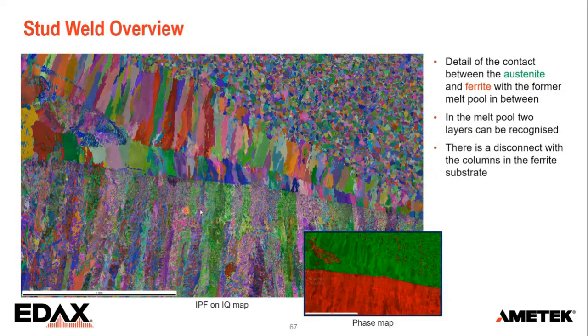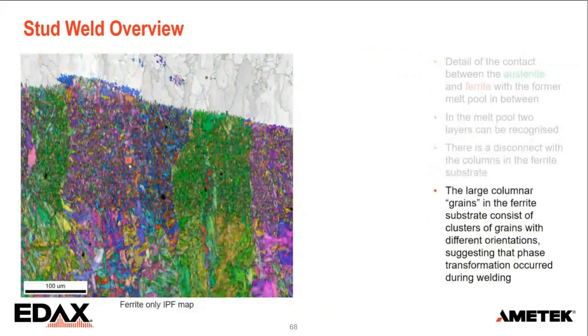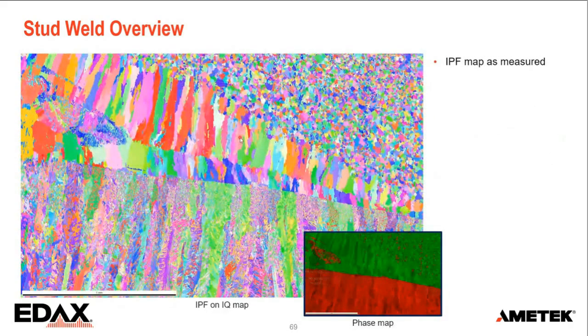And at the bottom, we have this columnar structure in ferrite, but that looks like lots of different grains instead of single ones. So if I just zoom into that, you can see that each column really consists of lots of different grains. And that suggests here that we had a phase transformation, that this actually formed as austenite that transformed into small ferrite grains with the different child orientations here at room temperature. And when we then apply the parent grain reconstruction, this is the original structure as measured, and after reconstructing it, we get this.